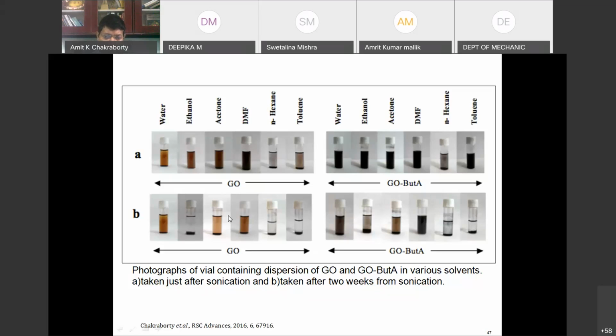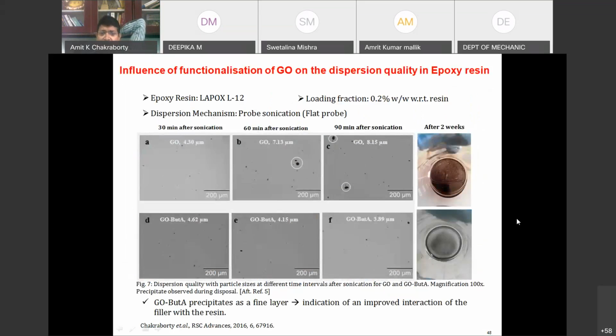But here with GO, it is even worse. None of them are stable except water, because GO is a very stable dispersion in water. No other solvent keeps GO well dispersed. So GO has a problem with dispersion except with water, but you cannot make a composite with water. Your composite will be made with some polymers, and the good thing is that the modified GO disperses very well in DMF, dimethyl formamide. It is absolutely stable as well as in water. So that was the advantage. And you can also see from the figures the particle size.